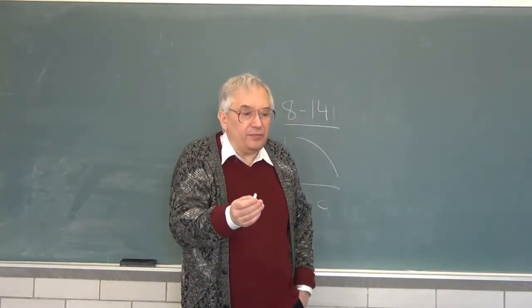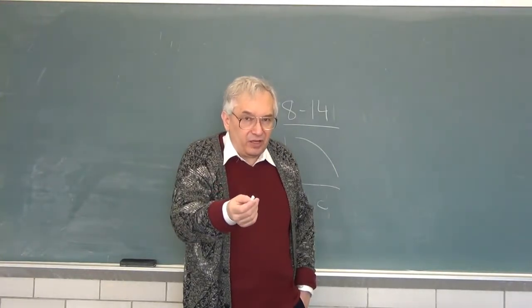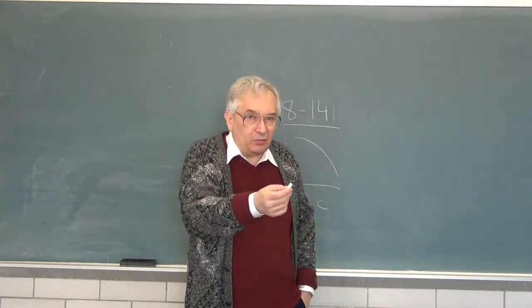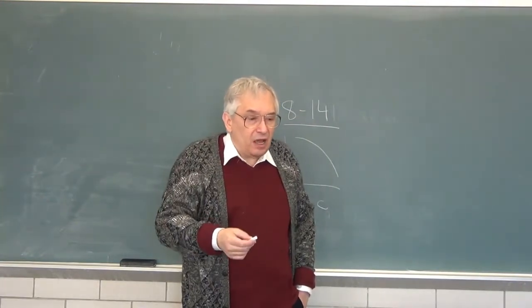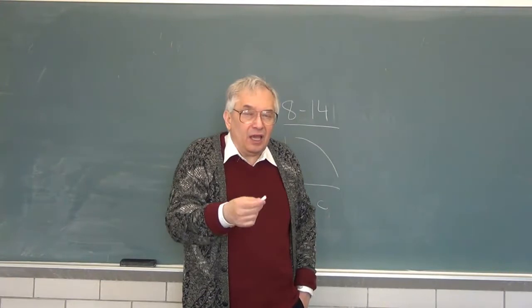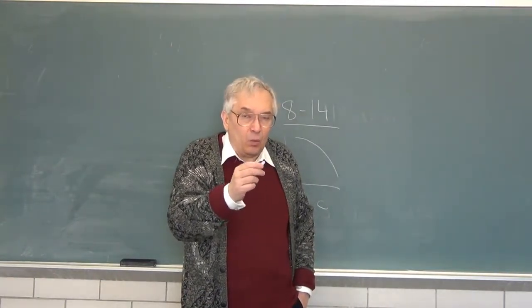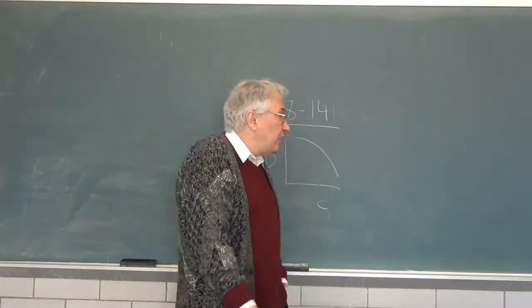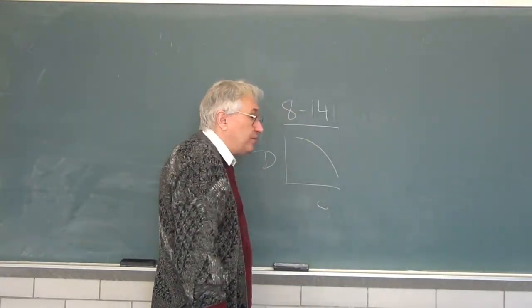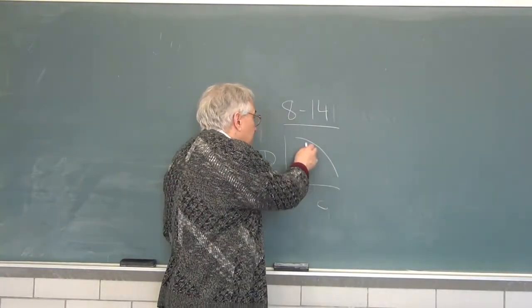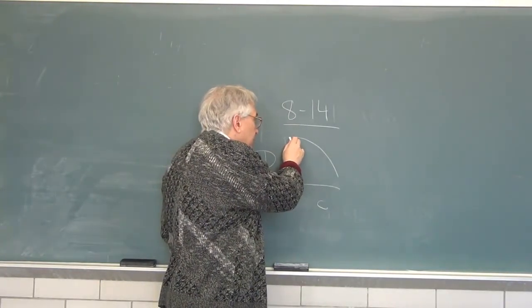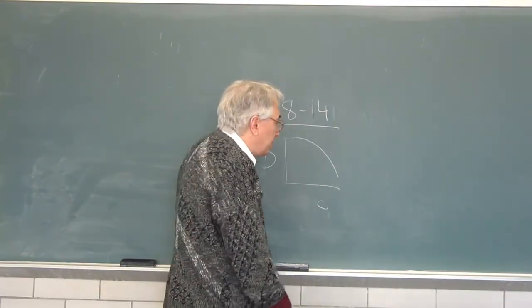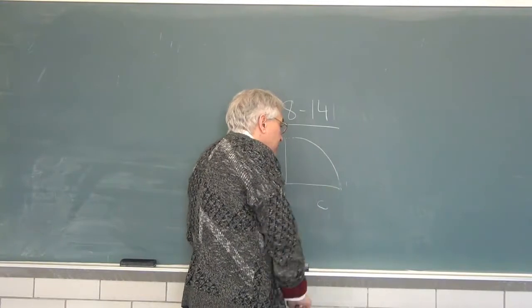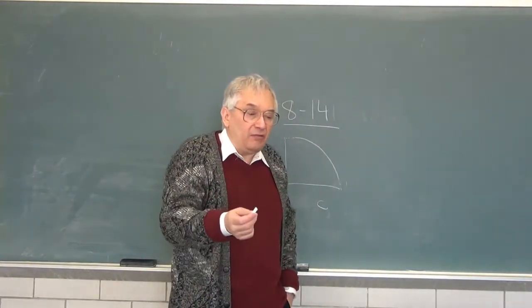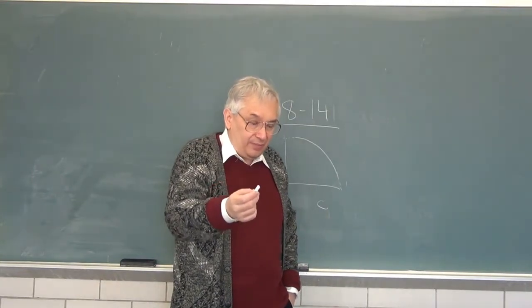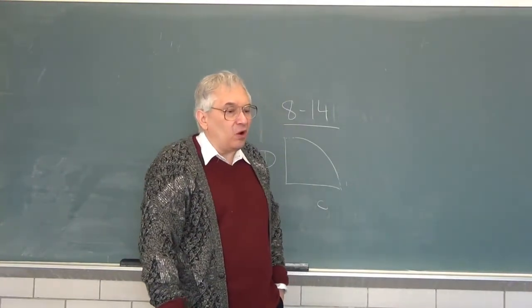Each of these studies looked at a whole series of concentrations, and they looked at a series of polymers of different molecular weights. Now, the first observation is that if you look at one polymer, one molecular weight, a series of concentrations, the measurements fall on a stretched exponential in concentration. You could certainly wish the measurements had been conducted down to very low concentration in all cases and had been conducted out as far as possible in high concentrations, but in every case, there is a stretched exponential fit. However, there's something more.